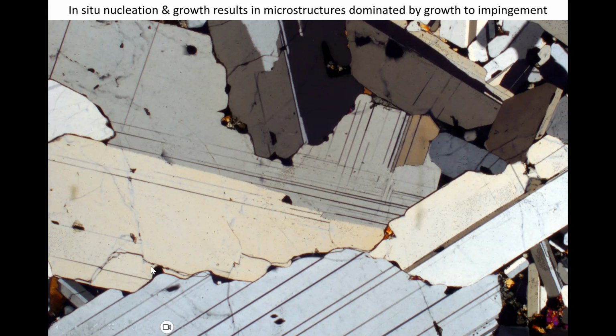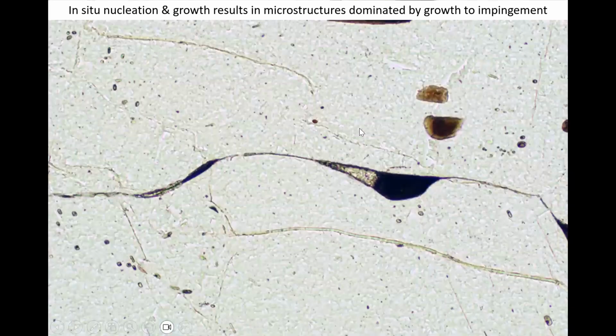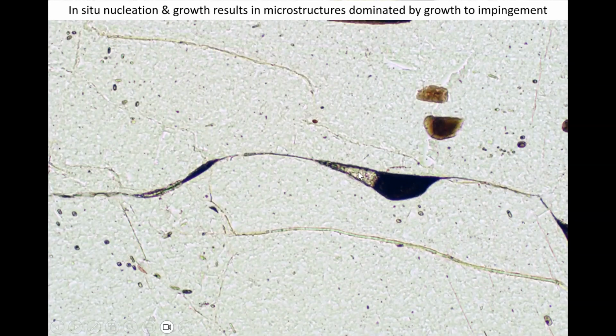And not only that, but you tend to get these undulations as they impinge together, and you get these melt-filled lenses. So this is a nodule, a crystalline enclave that was entrained by an Icelandic lava flow. So the solidification process has been quenched as it was brought up. So we see the grain boundaries bear no relationship to growth faces, and we've got these lenses, and we've got randomly oriented grains. And sometimes in those melt lenses, you can see they're just starting to be filled in with another phase. So this is two plagioclase grains, that's glass, and there's a little bit of clinopyroxene just growing in there.